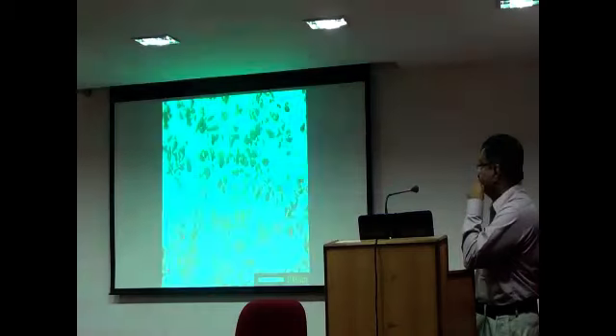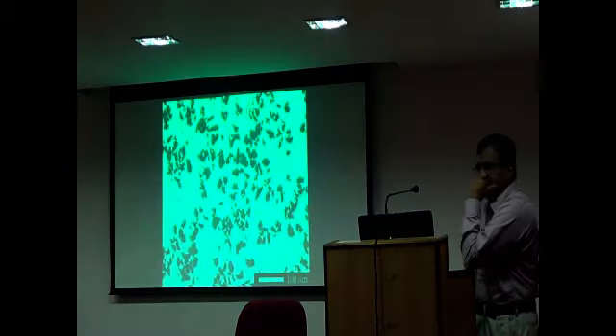It is vital that the ceramic particles are evenly distributed throughout the disc. Microscopic inspection of the cross-section verifies correct distribution. In the microstructure, the silicon carbide particles can be seen as dark patches.